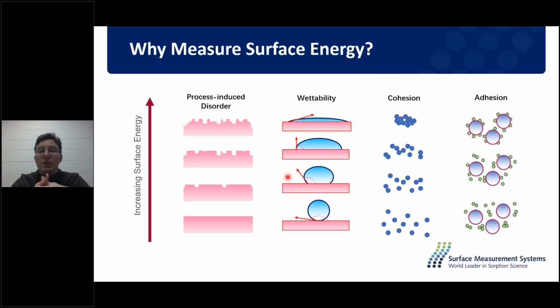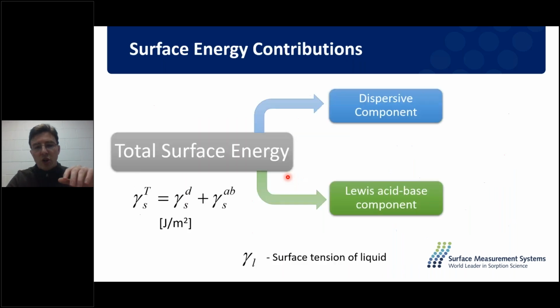We would also see a set of particles that have higher surface energy would be more likely to aggregate, more likely to form lumps, and would exhibit poorer flow properties. And when we have a multi-component mixture, we would see that this would have high work of adhesion as well. So more likeliness to bind to other particles of another composition. So within the system, we not only could measure one energy, we measure two energies. We measure the dispersive component, and we measure the Lewis acid base component, or the polarity of bonds.